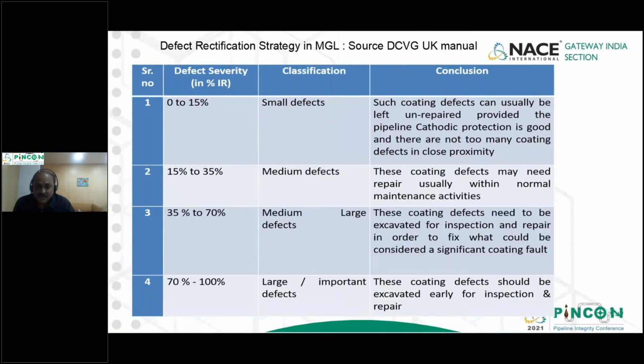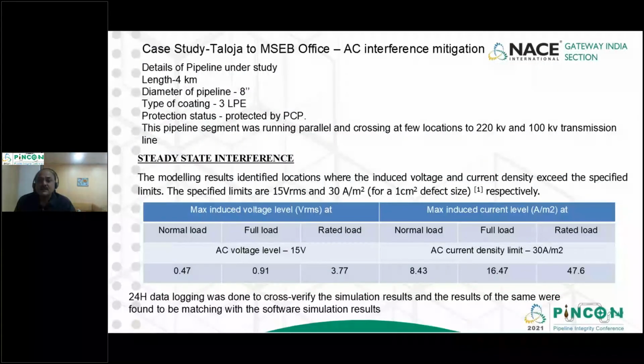Between 35 to 70% defect severity, that is medium and large defects, we excavate, inspect, repair, and fix whatever the coating defect is. And between 70 to 100% are large defects, these we do immediately, and we try to finish them within that particular season itself. Now these are a couple of case studies which I'll be sharing with you.